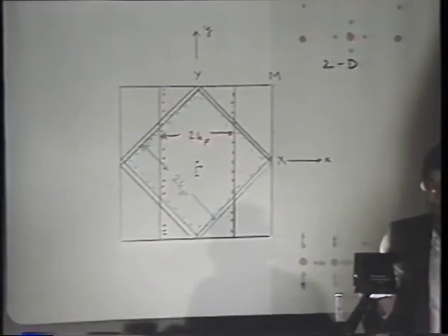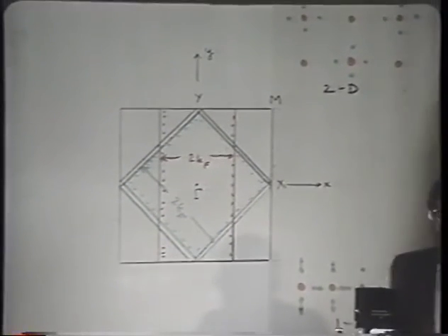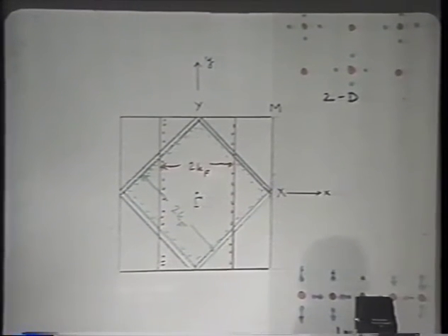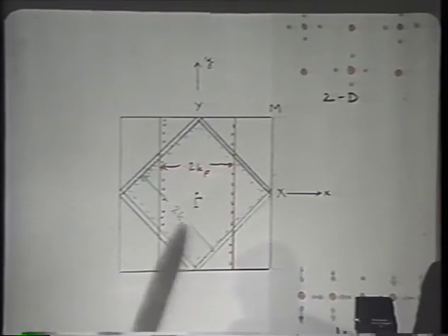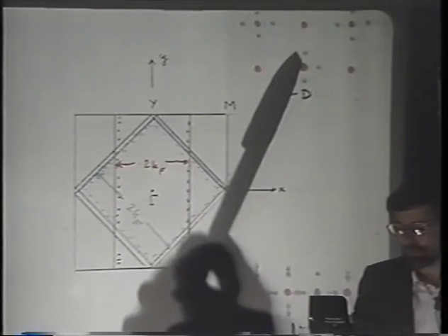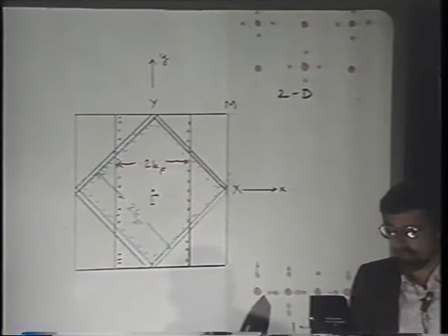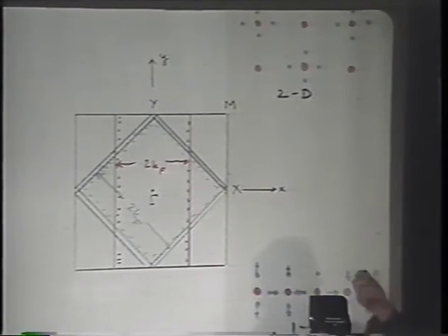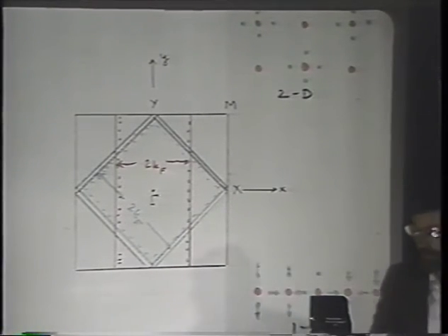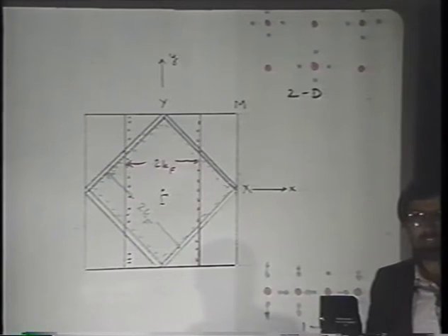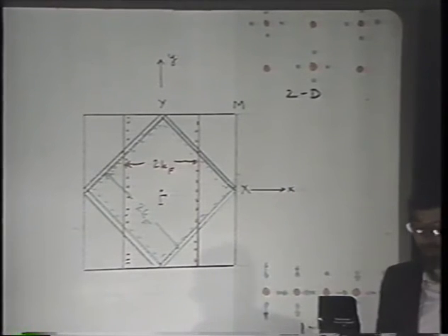As was pointed out first by Len Mathis, there is only one type of mode in the system which couples to first order to the states at the Fermi level, and that is the breathing mode. Here we have two-dimensional breathing modes with the oxygens breathing in and out around the copper atoms. In addition, we now have one-dimensional breathing modes along these chains. These would be the longitudinal modes, and transverse modes of oxygen atoms, these backbones of the chains moving up and down.